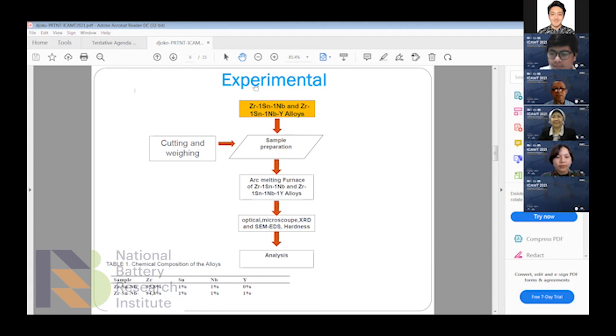Experiment. This is the alloy sample preparation, cutting and weighing, and then I use an electric arc melting furnace to melt the elements of the alloy. The melting point of zirconium is around 1850 degrees centigrade. The electric furnace has a capability of up to 3000 degrees centigrade. After melting, the material is characterized by optical microscope, XRD, and SEM-EDS, and also hardness of the material.